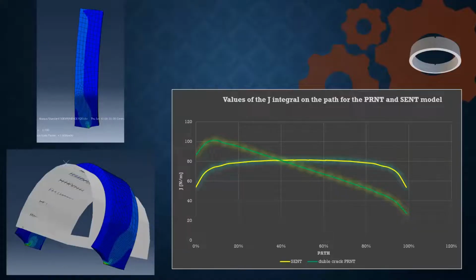On this slide, we can see a comparative dependence of the value of the J integral on the path for the PRNT and SENT models. The quasi-static load of the PRNT and SENT specimens, actually models, was simulated using FEM, in order to determine the ratio of the values of the stress intensity factor. The diagrams show that the distribution along the ring is uneven, which is to some extent expected, having in mind the geometry of the test specimen.